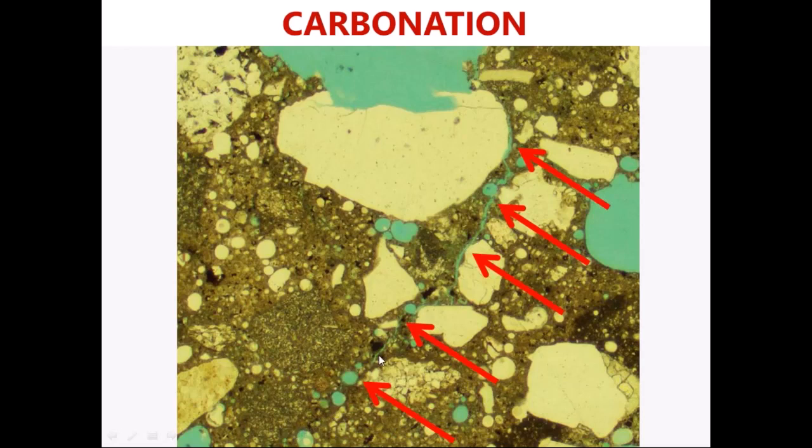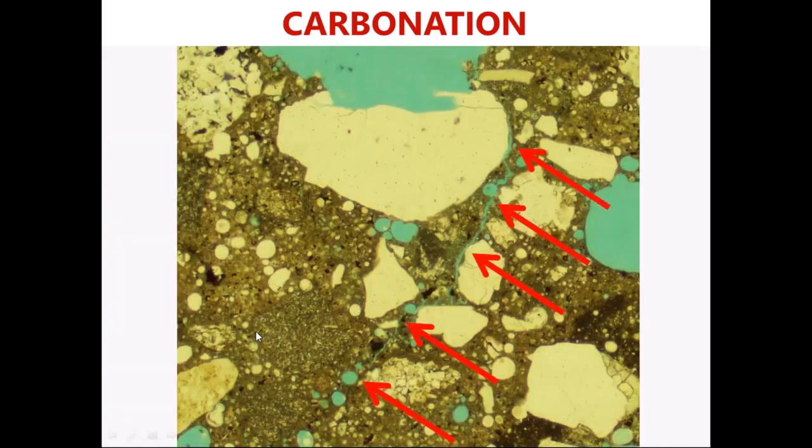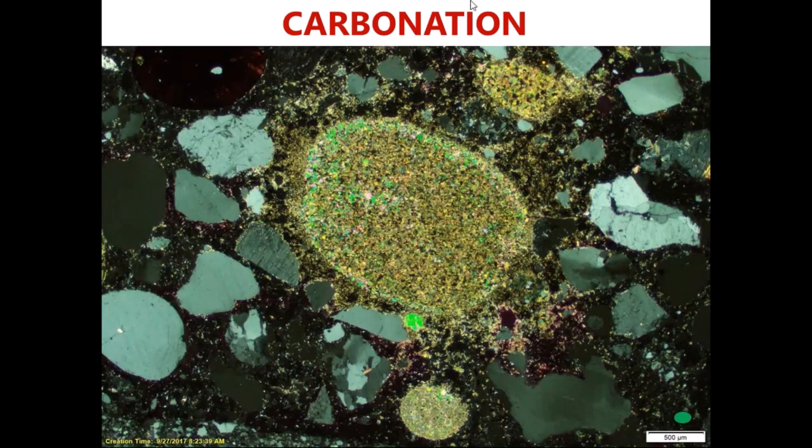And that bleed water crack essentially acted as a pathway. It's like a little highway where all the water and oxygen got in from the atmosphere and carbonated the paste around it. Therefore, there's the crack, and it extended all the way down here. Therefore, the paste carbonated on all sides of that crack. That's why it was deeper there. So I'll point that out as well.